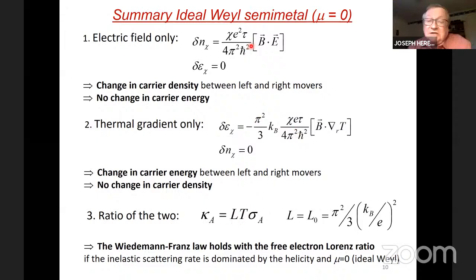By the way, the ratio of the two, extra energy over extra carrier concentration, actually follows the Wiedemann-Franz law with the free electron Lorenz ratio if we take these scattering times to be the same. In other words, there is only one scattering time in the problem, and that is the inter-Weyl point scattering. Of course, if the thermal scattering time, the inelastic scattering time, were different from the scattering time for charge transport, then we would have a different situation. But if they're the same, then you end up with a free electron Lorenz ratio.